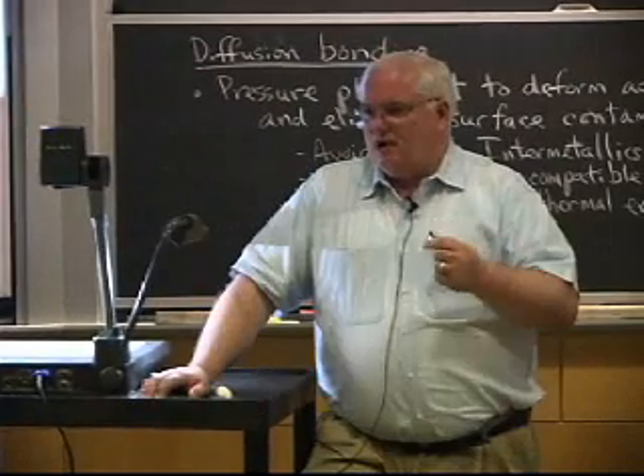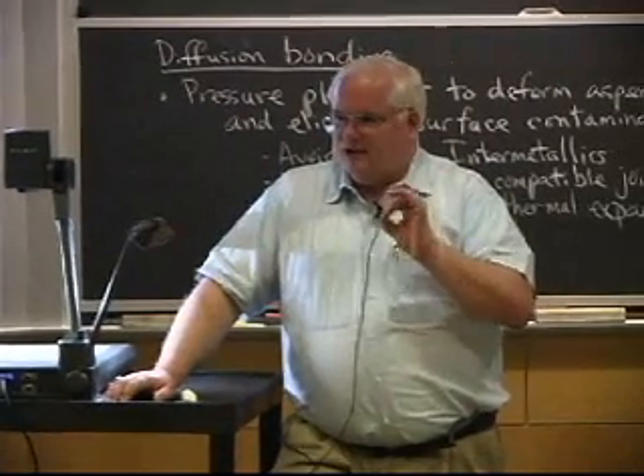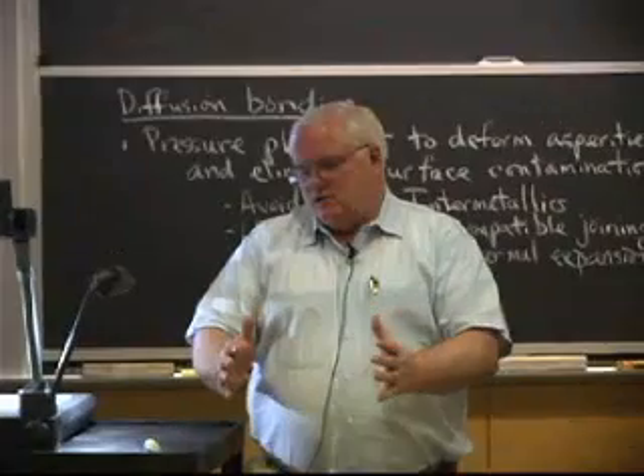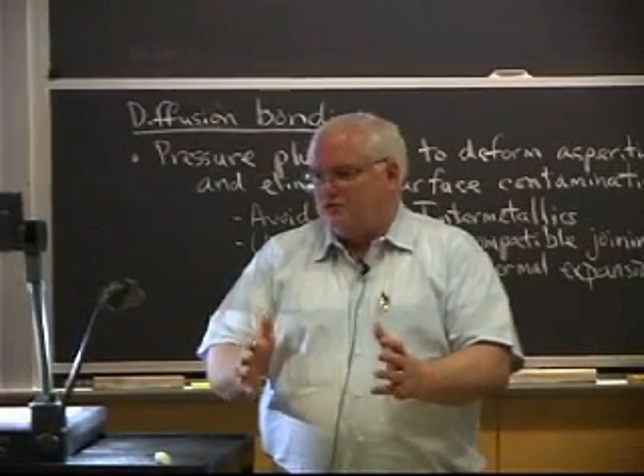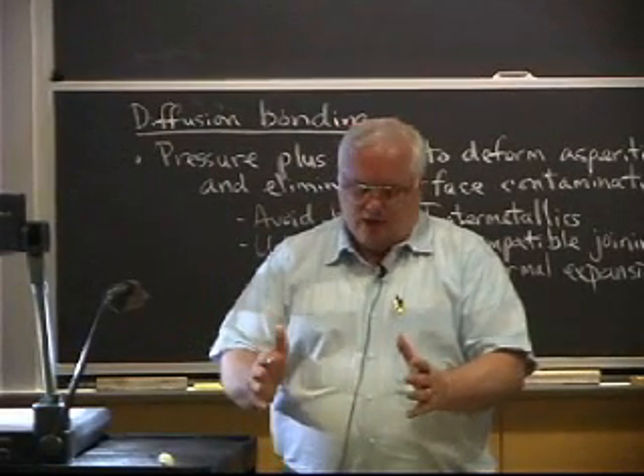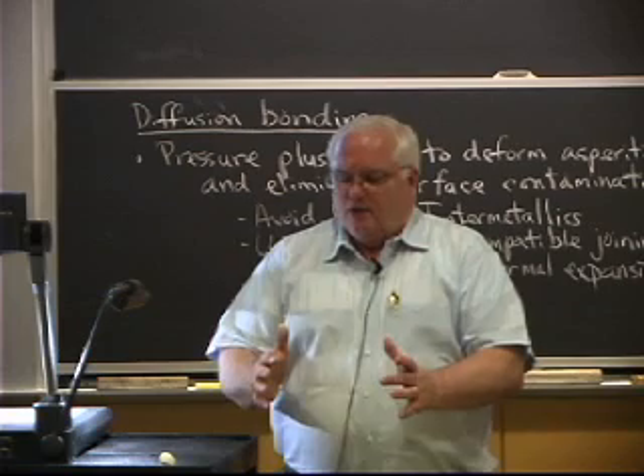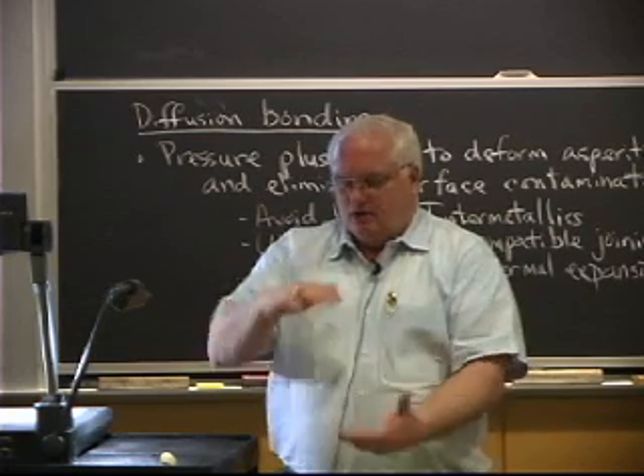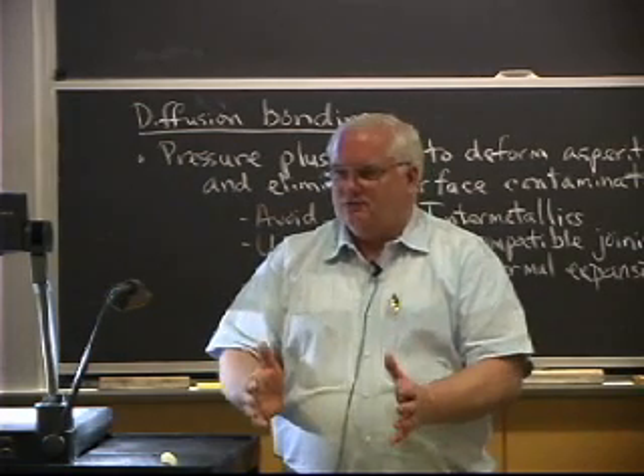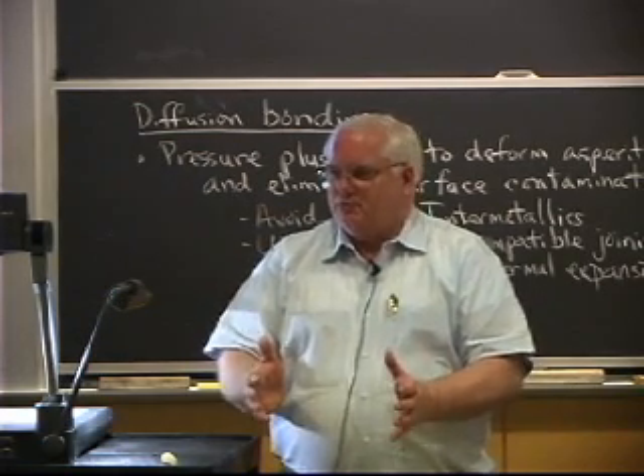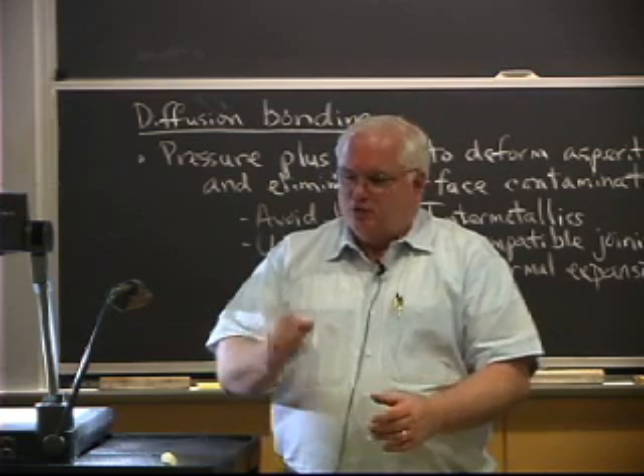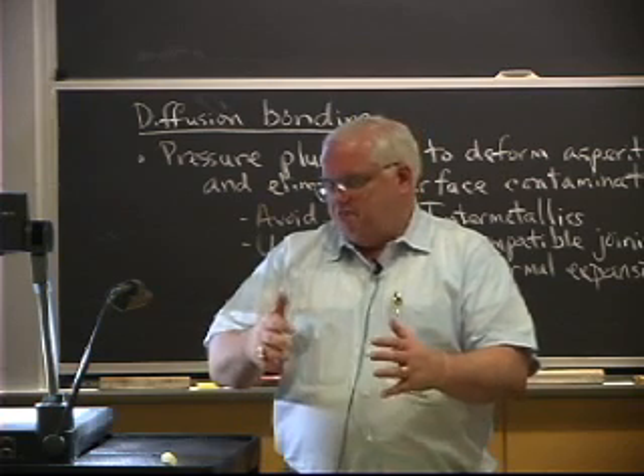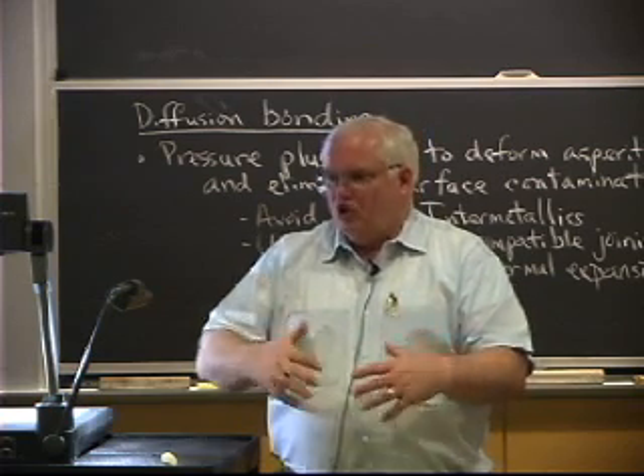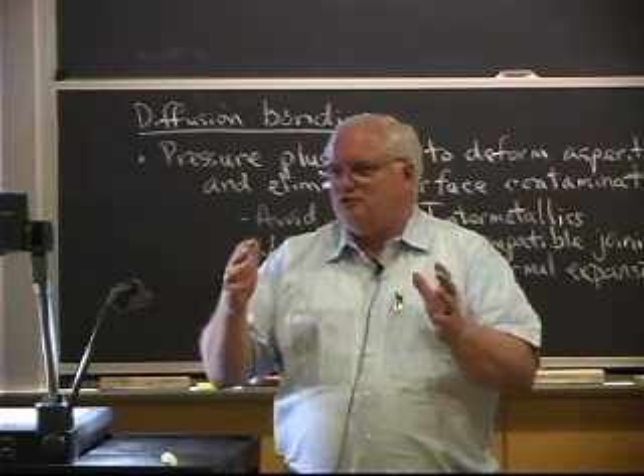To get this thing started, it doesn't take very much, in a small area. You guys probably haven't seen a thermite weld, but you can have a container this size full of this powder, which is almost dirt cheap. It's just iron oxide and aluminum. You ignite it, and within 5 seconds, the whole thing heats up to around 2,000 degrees centigrade.